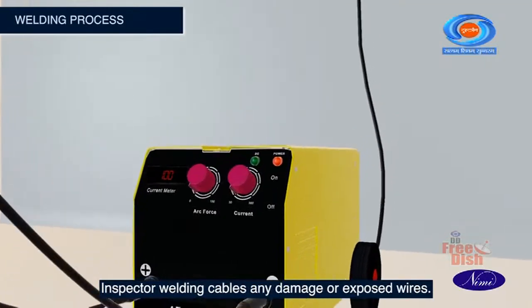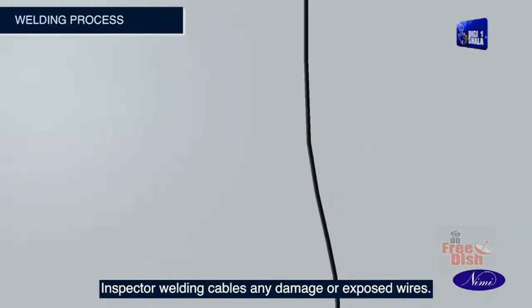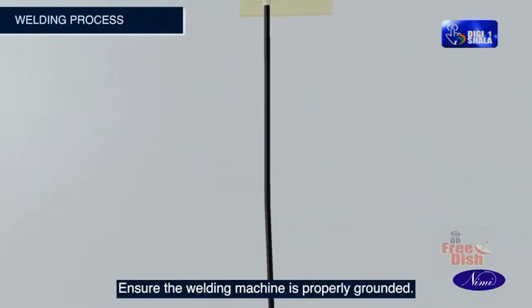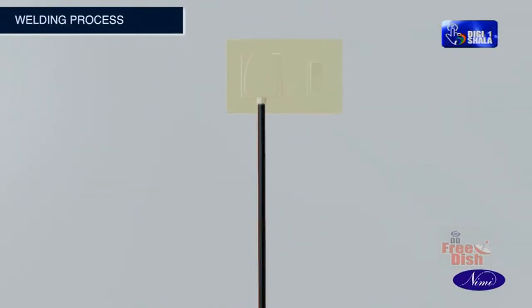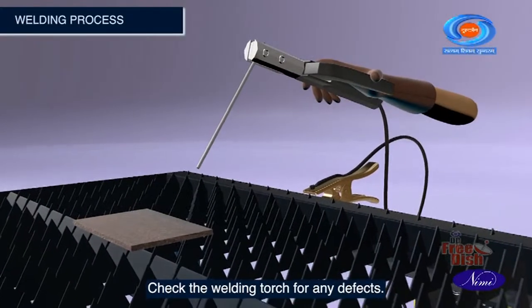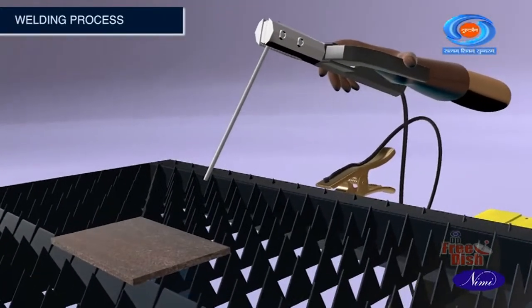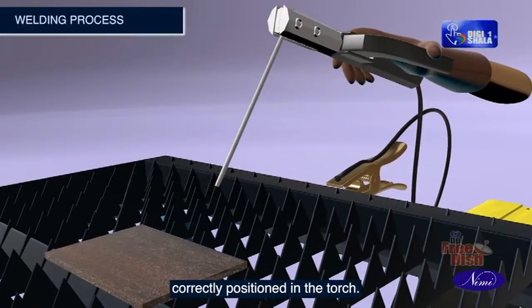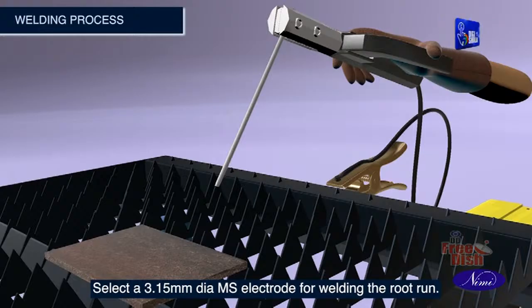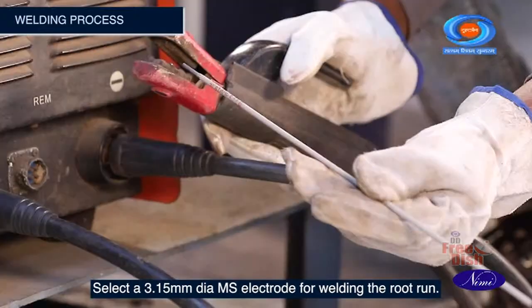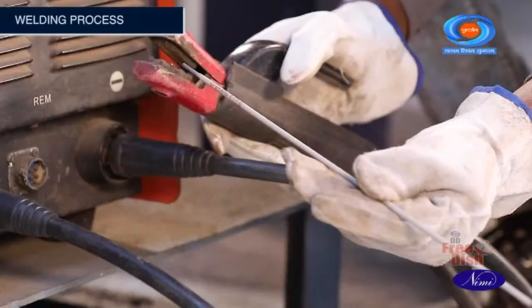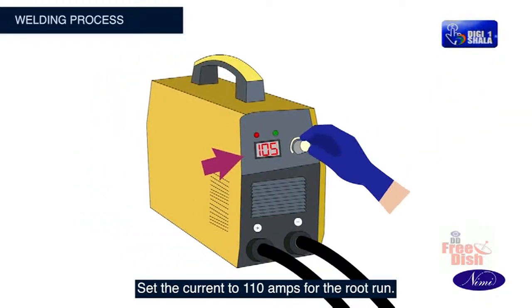Inspect welding cables for any damage or exposed wires. Ensure the welding machine is properly grounded. Check the welding torch for any defects. Ensure that the electrode is correctly positioned in the torch. Select a 3.15 mm dia MS electrode for welding the root run. Set the current to 110 amps for the root run.